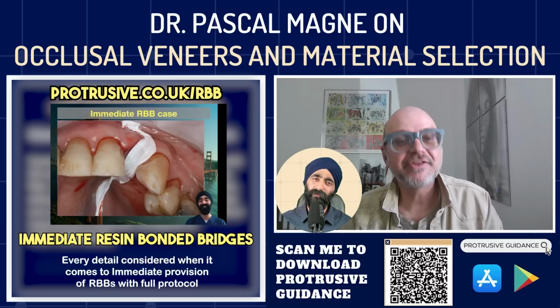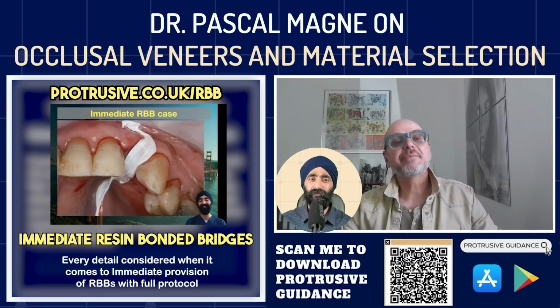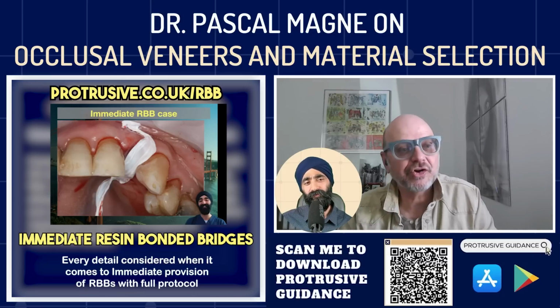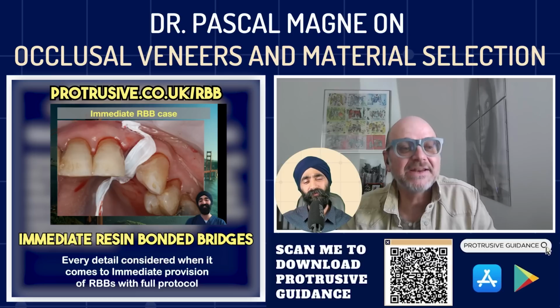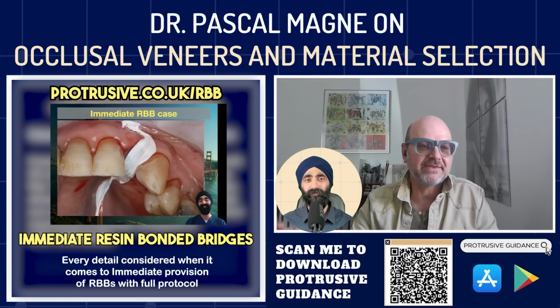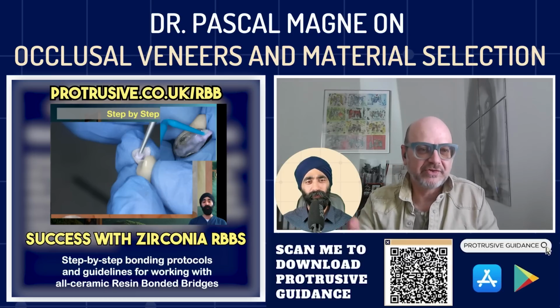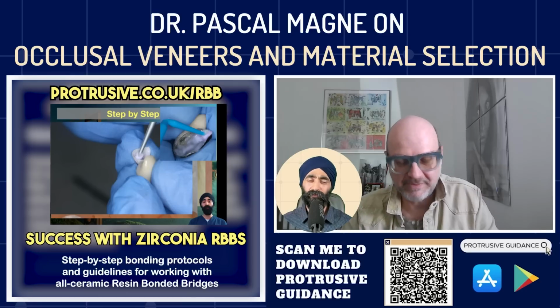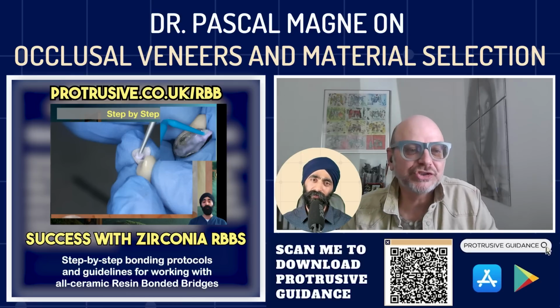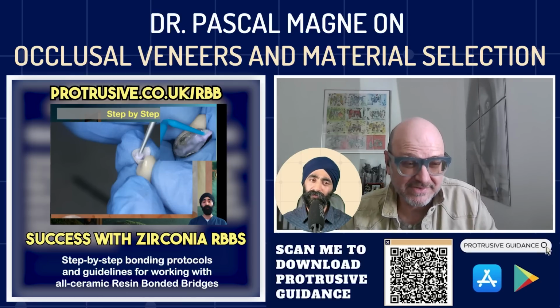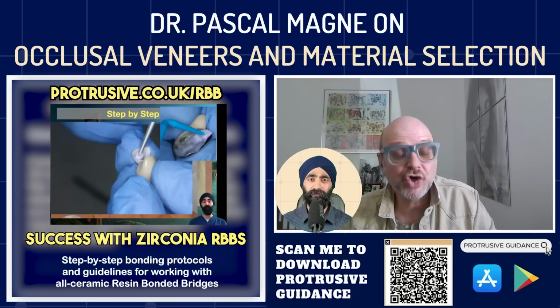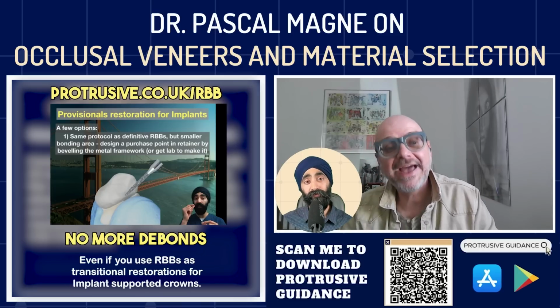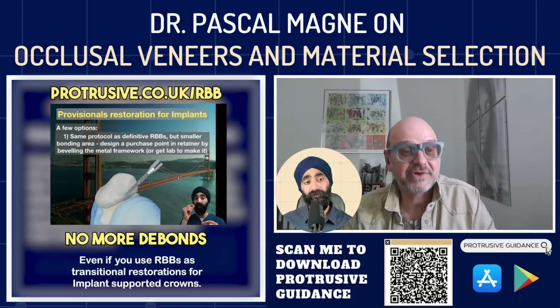Now we have a new problem. And the new problem is the printed materials, because the printed materials have low filler content. They have barely above 50%, so that those materials can be sold as a crown material and reimbursed by insurance. But they are not as good as the CAD/CAM materials. And this is going to hurt until we have highly filled printable material.